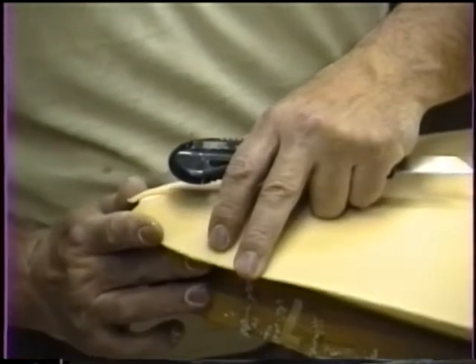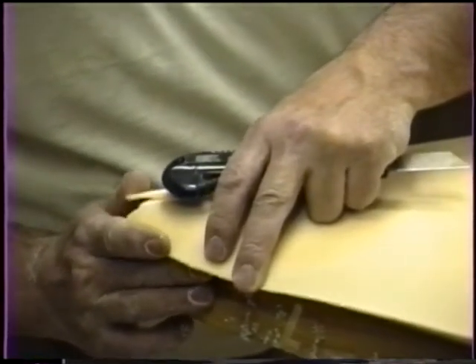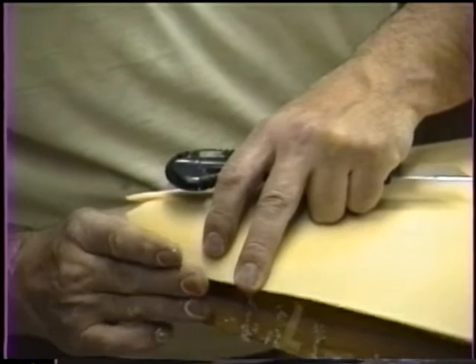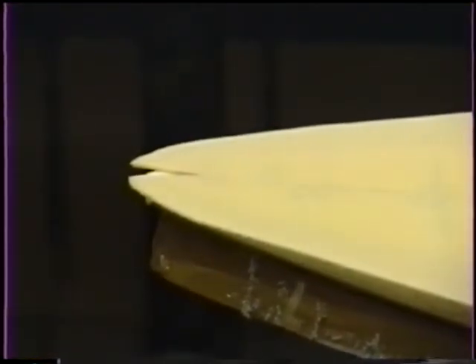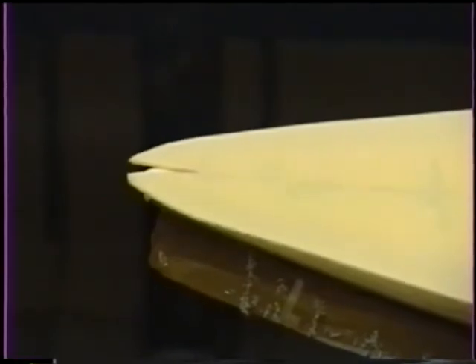When the high density foam is bent around too tight a curve, it will crack. A good tip is to add a wide strip of masking tape to the outside of the high density foam at the most curved spots to reduce cracking.